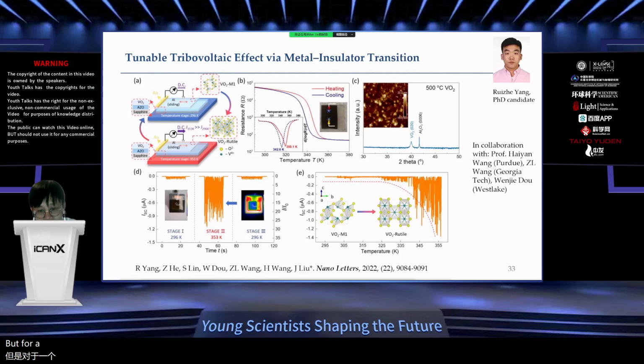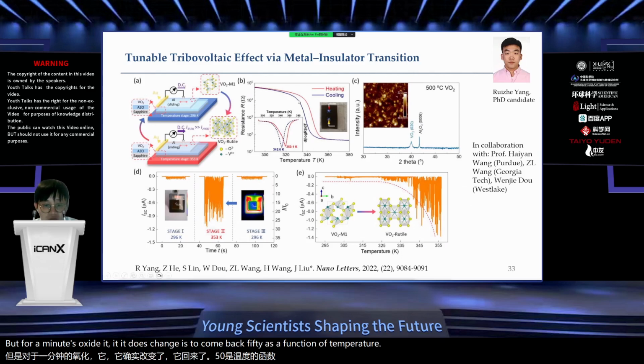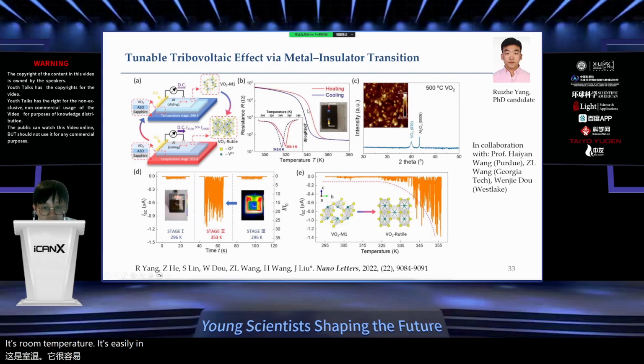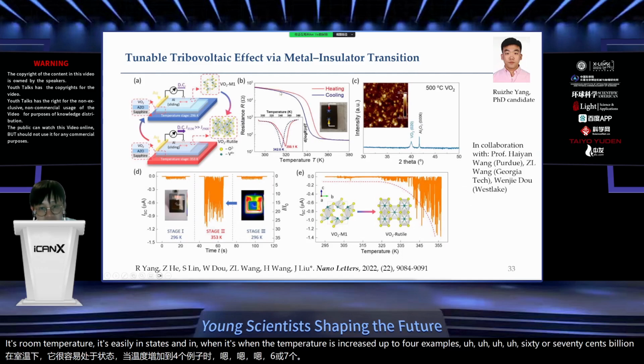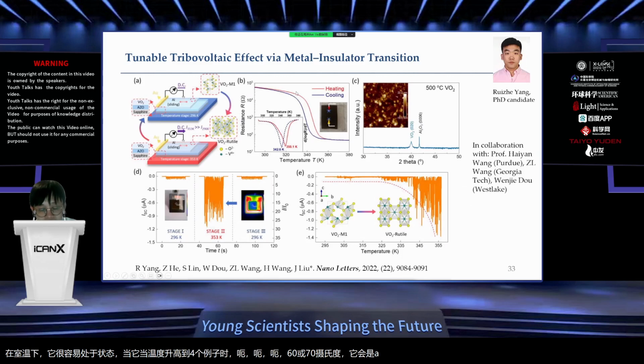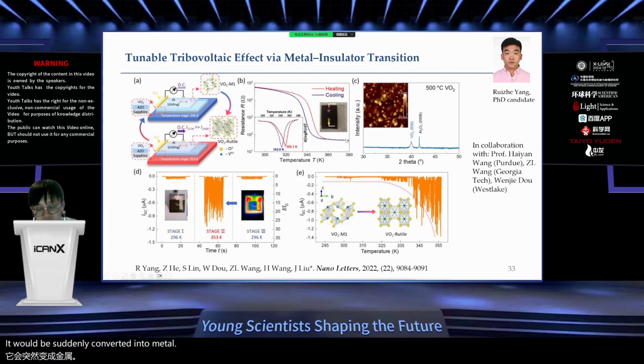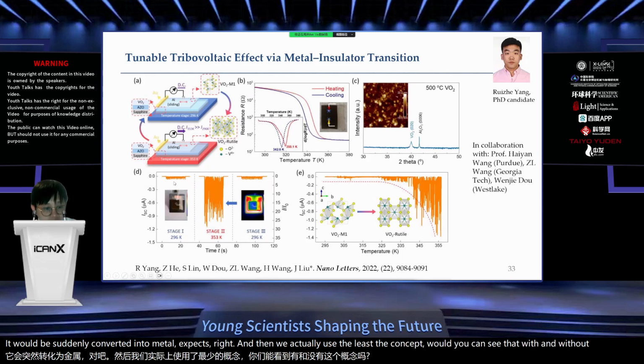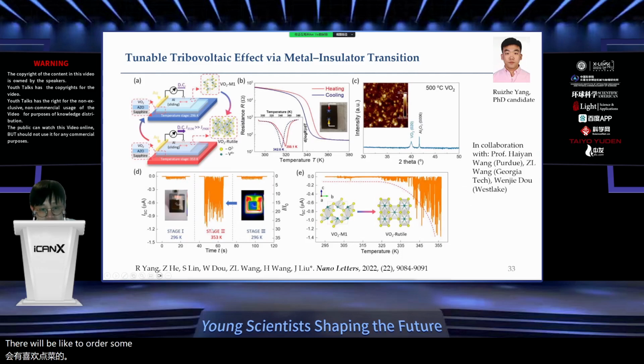Vanadium oxide changes its conductivity as a function of temperature. At room temperature, it's in an insulating state, and when the temperature is increased up to, for example, 60 or 70 degrees Celsius, it is suddenly converted into a metallic state, right? And then we actually use this concept, and you can see that with and without heating, there is about 2 orders of magnitude difference in DC output, right? When you have another metal sliding on top.